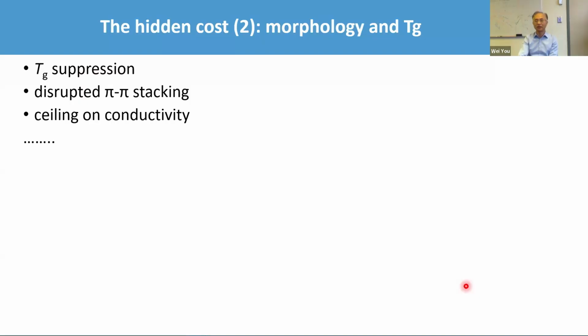The second, which we spent some time to think through, is that having the side chain also brings some other detrimental effects, or let's say inconvenience, to the materials. First of all, possibly the Tg, glass transition temperature, will be suppressed. I'll talk about that in a few seconds. The second is that by having the side chains, you disrupt the pi stacking, which you possibly need for charge transport. But back to my earlier point, you do want to have a side chain to break them to a certain extent. Otherwise, you won't be able to dissolve them, right? Then third, you now have a ceiling on the conductivity because you are not having 100% conjugate polymer in your finished film, because 50% is essentially insulating.